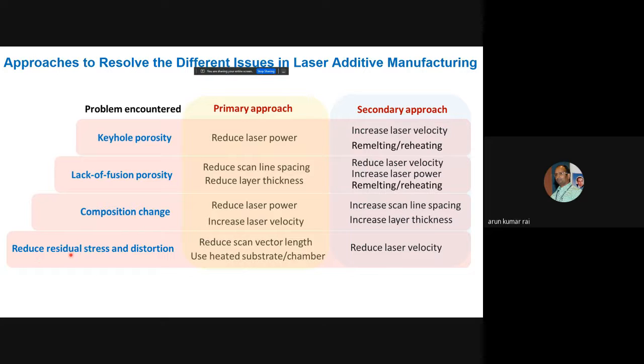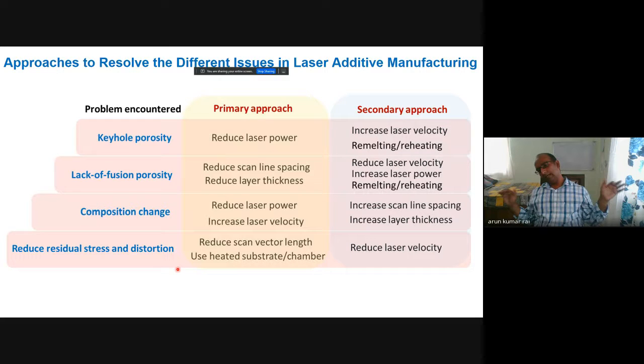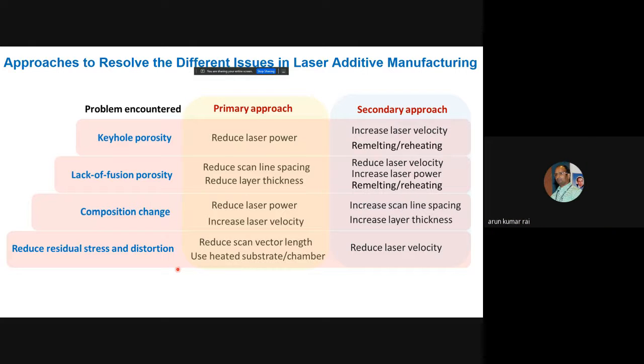Then next is residual stress and distortion. In additive manufacturing, this is one of the biggest challenges, basically residual stress. And why does residual stress come? Suppose on the substrate you are depositing some material, so the substrate has heated and your powder has melted. Some neighboring area of the substrate which is not melted has a lower temperature. The powder is cooling from the melt, so it is contracting, but your substrate is expanding. So the contraction of the melt pool and expansion of the substrate lead to formation of the residual stress in the build component.